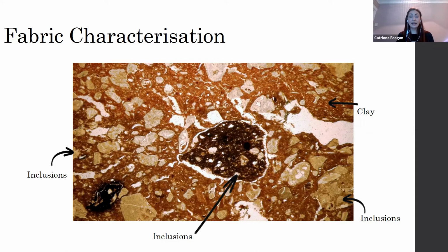Generally, inclusions can either be naturally present. Whenever we talk about naturally present inclusions, this can be stuff like fossils or organic material or stones, just stuff that's naturally incorporated into the clay. And often, unless the clay is very purified and sieved and cleaned, at least some of this stuff will remain within the sherd. The other type of inclusion is called temper, and this is an example of temper. This is a piece of chamotte, which is broken down old sherds of pottery, which have been ground down and then just added to the clay mix.